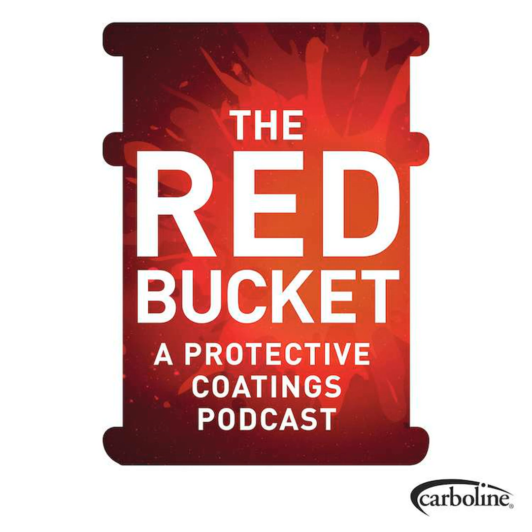So if you think about metalizing and galvanizing, it's essentially 100% zinc. As I mentioned a little bit earlier, metalizing oftentimes will use an alloy with aluminum, upwards of 85% zinc to 15% aluminum. And of course, there's some zinc iron alloy. And with the metalizing, you oftentimes are a little bit thicker, I'm thinking over 10 mils. That's all zinc or a little bit of aluminum.